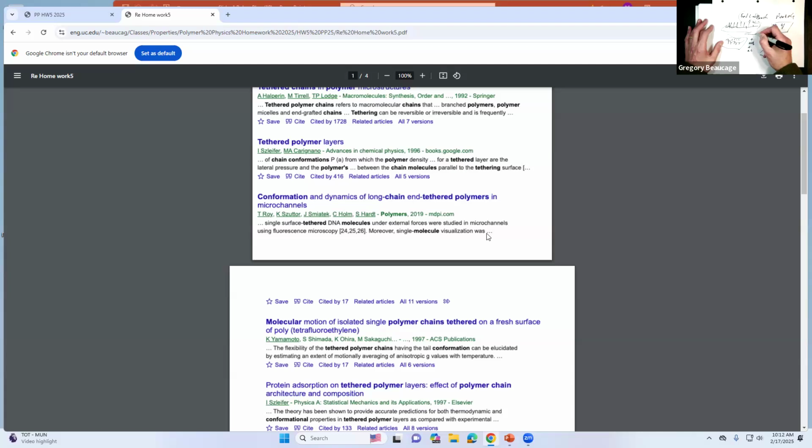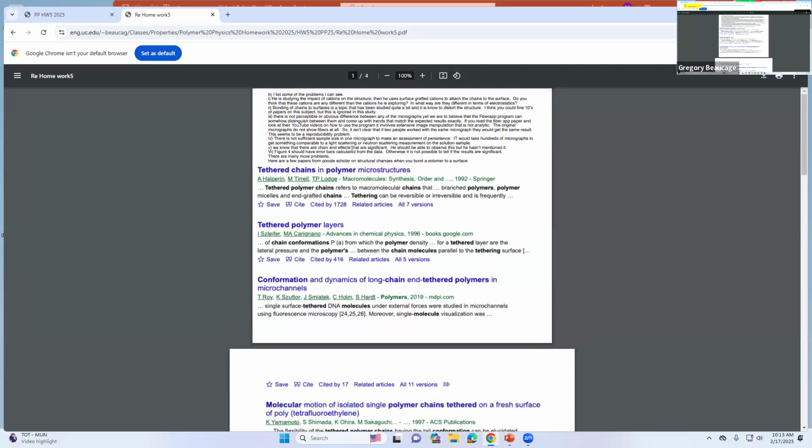Then he's got this anion, the carboxylic groups, and he's looking at how the conformation changes when he adds something like Mg2+, a cation. So he's got a cationic surface. He's studying this and then putting it onto a cationic surface, which doesn't make any sense. That's exactly the feature he's trying to measure, and what he's using to tether the thing to the surface changes the conformation. The more you look at it, the more you can see there's some craziness involved in this. It's surprising it didn't come out in review, I guess.